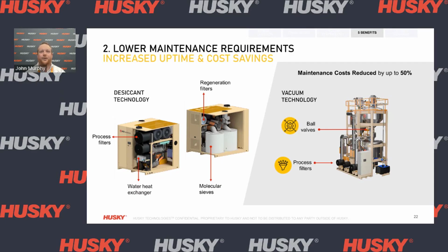We see, for example, the molecular sieve towers, when running recycled material, should typically be changed out every 3 to 5 years, which can be quite expensive. And we also see that the water heat exchanger needs to be cleaned quite regularly, every week or 2 weeks. And as well, the process filters are items that do need to be maintained, typically every week to 2 weeks.